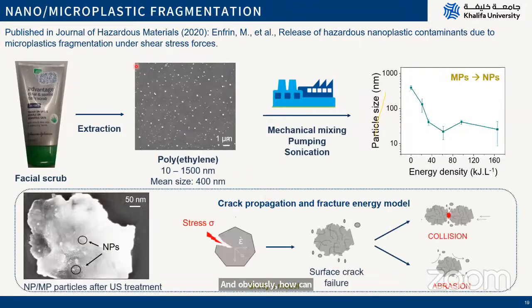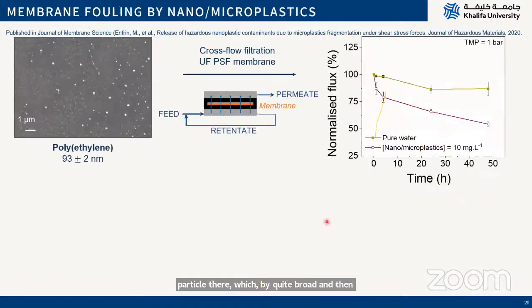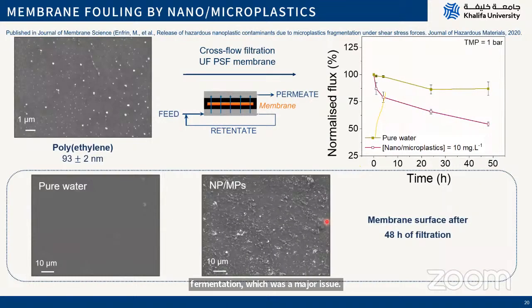So we used this face scrub, extracted the polyethylene particles there, which were quite broad, and then characterized the particles, and found quickly that we had fragmentation, which was a major issue. So we looked at controlling this fragmentation and then generated microplastics of fixed diameters, around 93, 95 nanometers, and we used them for water filtration purposes. I will not go through all the details there, but we have published that, so if you have any questions, you can come back to us and ask after.